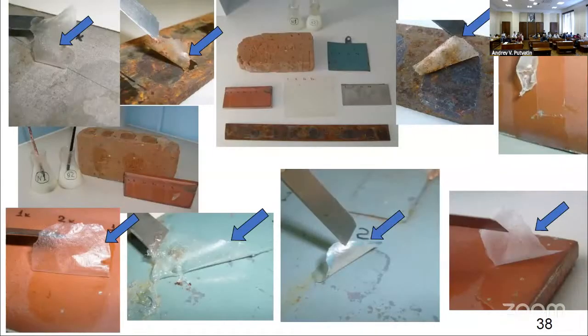Normally, these polymeric films are treated with a water solution. Usually, for application of polymeric films, we use polyvinyl alcohol in water solution. We can include special chemical additives which dissolve surface contaminations, and after formation of the polymeric film, all contaminations are included in it, and then we can remove this polymeric film from the surface with the fixed contaminations.